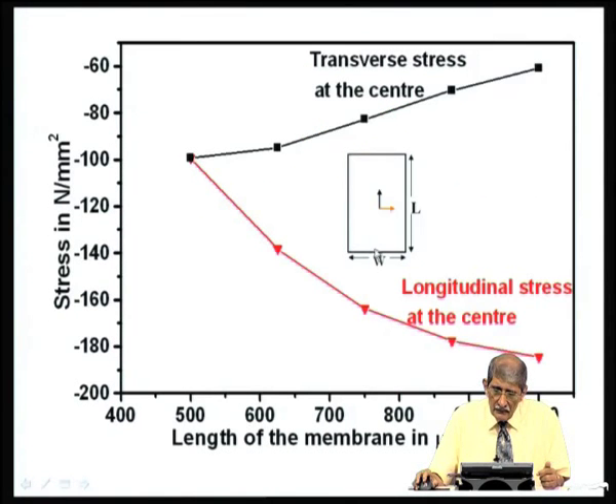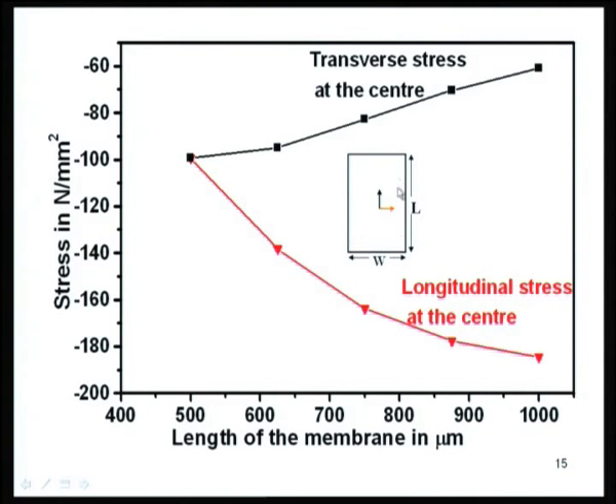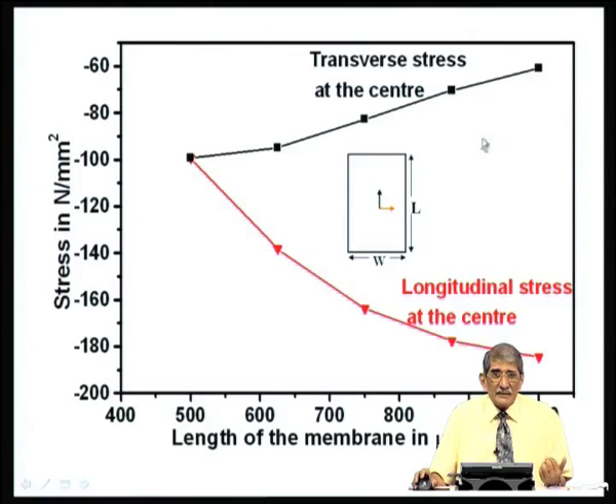Similarly, if I take the resistor at the center, there the stress is compressive. So, I have shown it as a negative value. As I increase the length from 500 to 1000, the longitudinal stress goes up from minus 100 to close to 200. So, if the aspect ratio L by W is 2, the compressive stress here is almost a factor of 2 higher. Now, this resistor also has longitudinal compressive stress, but the stress in the transverse direction actually becomes less, which is good, because if there is stress in the transverse direction, that will actually reduce the effect of the longitudinal stress.